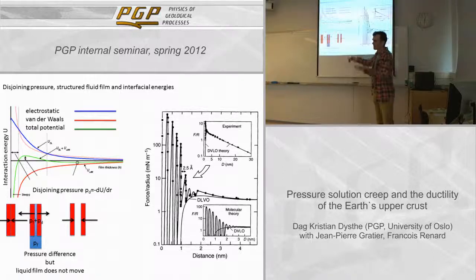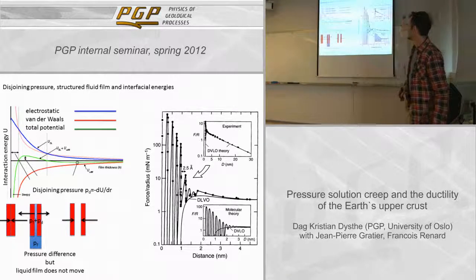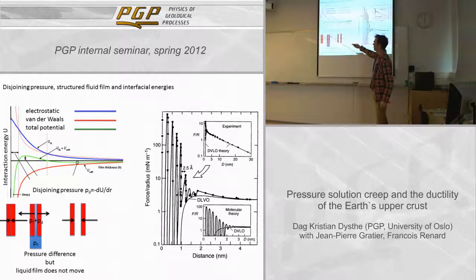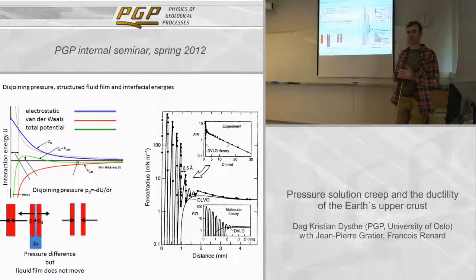So this is kind of the basis for the fast matter transport out of the region where dissolution is happening. If there was no fluid there, if you get to this situation, the diffusion rate out of such a grain contact will be many orders of magnitude slower. And then pressure solution would have been a much slower process and less efficient, and it would not be possible to compact sediments until you got much deeper and you could plastically deform the grains.